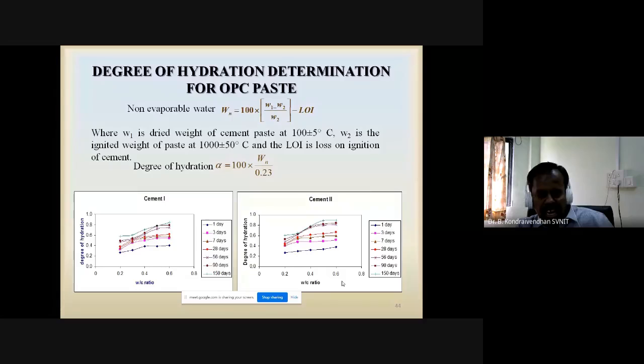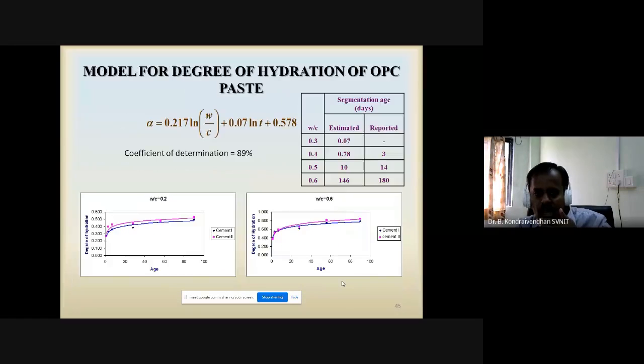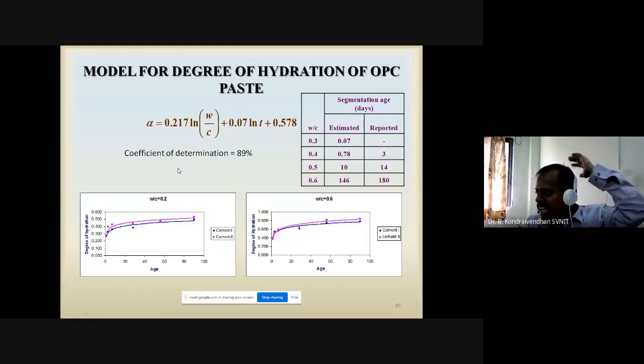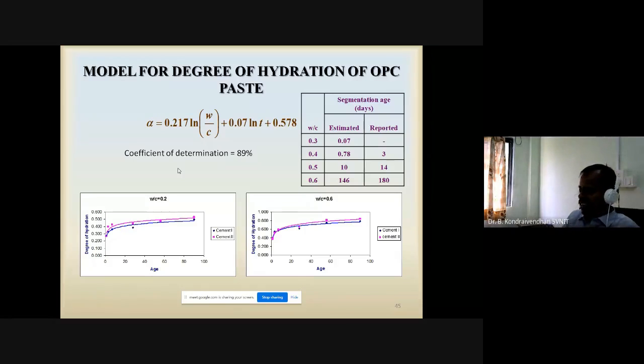Then, using this data, we also did some least square based regression analysis, and we got the degree of hydration as a function of water cement ratio and curing age. Now this kind of equation is available. By using this equation in the capillary entry radius, we now get the capillary entry radius as a function of water cement ratio, curing age, and mean cement particle radius. So one can determine the mean distribution radius, or R50, for the capillary entry radius using these 3 parameters. You only have to give the input: the water cement ratio, the curing age you want, and the mean cement particle size. If you provide these 3 parameters, you can calculate the capillary entry radius.